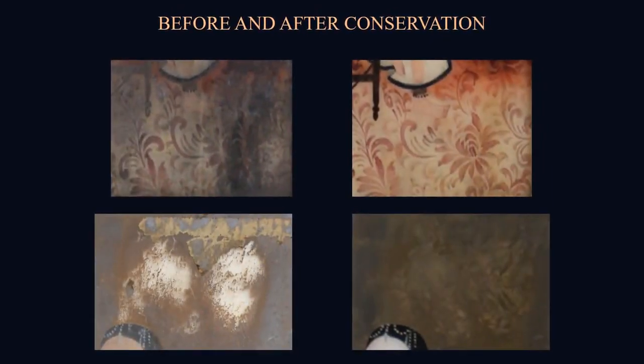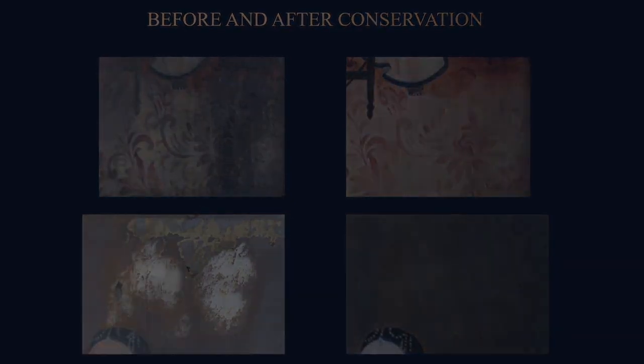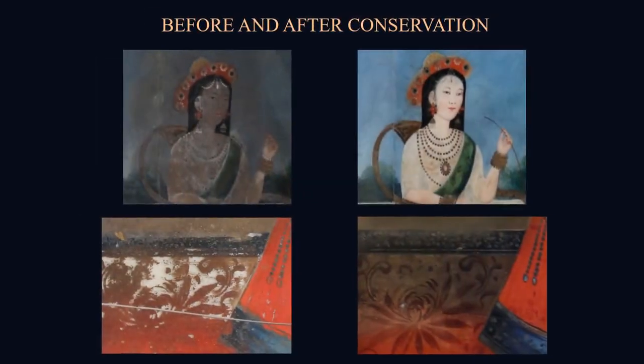These are some images of before and after conservation treatment, which show how stains and fungal spores have reduced, and reintegration of the paint layer is also done. As you can see, the broken edges of the paintings are now properly aligned and glued. The same areas display the original colors incorporated in the painting and are much clearer after the tarnishing is reversed. And the paint layer has also settled down after full consolidation.